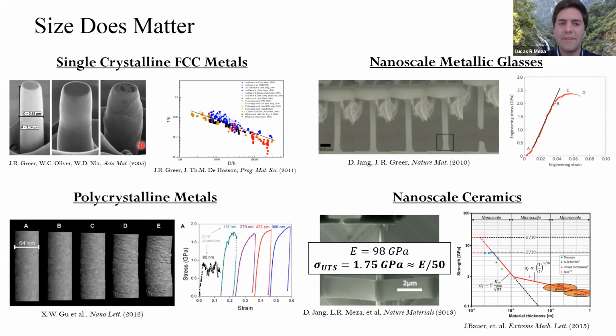The mechanism for why smaller is stronger is you have a statistical elimination of dislocations - smaller things are more likely to be single crystalline. And you have a free surface where if you do have dislocations, they can escape out of. So both of those still hold regardless of whether it's FCC, BCC, or HCP.